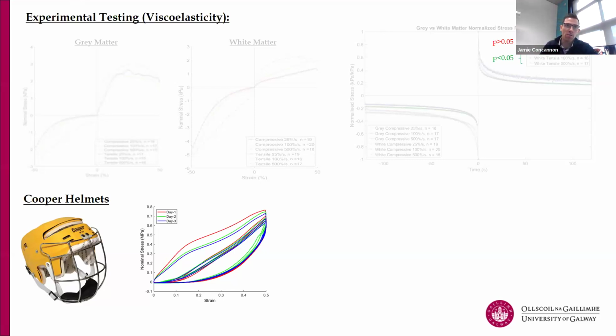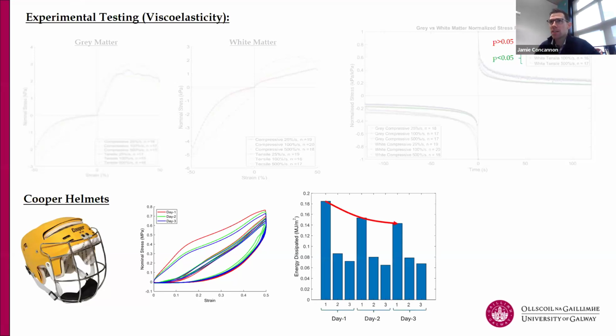So if you look at the red loading curve, which is on top, and then as I relax that material, it starts to decay here, and we call this a hysteresis loop. But this really interesting trend emerged in that the energy dissipated from cycle 1 and day 1 was the highest. And then once you went to cycle 2 and cycle 3, it nearly halved the amount of energy dissipated.